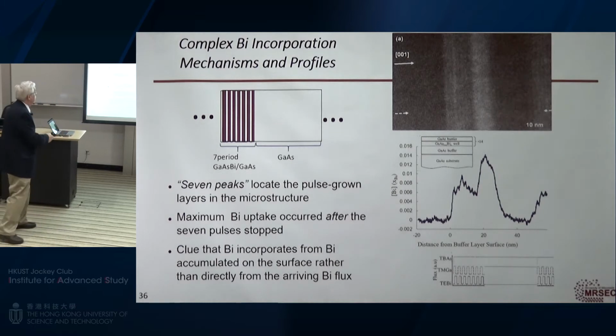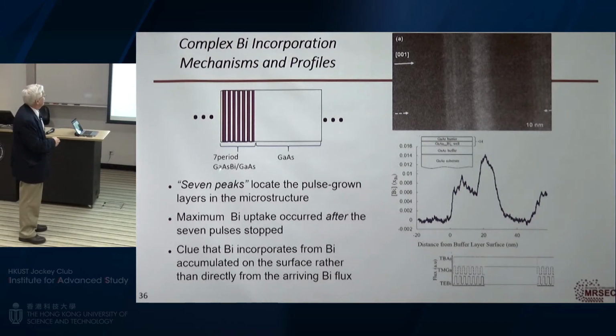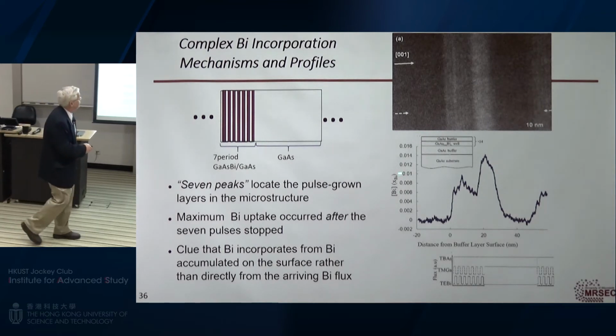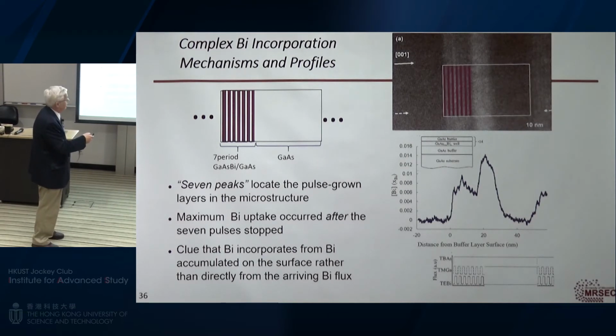In order to investigate that, what we did is we grew a sample where we just put bismuth in the system, out of the system, in the system, out of the system in the vapor phase, and then grew a layer that had no bismuth in the reactor. And we saw something very unusual. You can see these are the layers with bismuth in it, and bright here means bismuth. While I'm putting bismuth into the system, you can see I get bright, bright, bright.